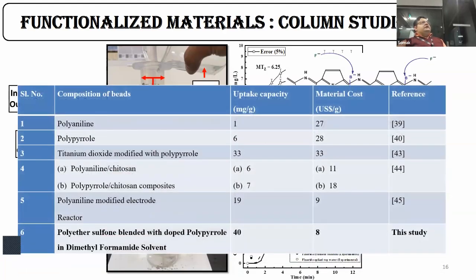We also carried out an analysis of uptake capacity versus material cost. With doped polypyrrole in DMF solvent, the uptake capacity was nearly 40 at 298 Kelvin, that is 25 degrees Celsius, and the material cost was around $8 per gram. In comparison, most polymer structures like polyaniline and polypyrrole have high material cost but comparatively low uptake capacity. The only one close is titanium dioxide modified with polypyrrole, with an uptake capacity around 33, still lower than what we achieved, and its material cost is also comparatively high.